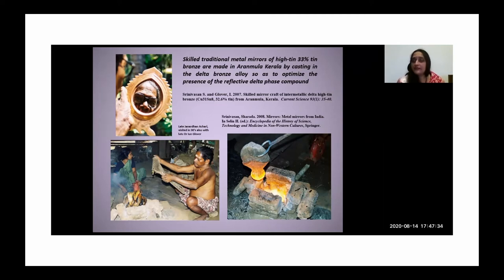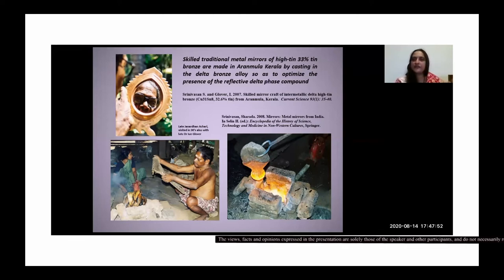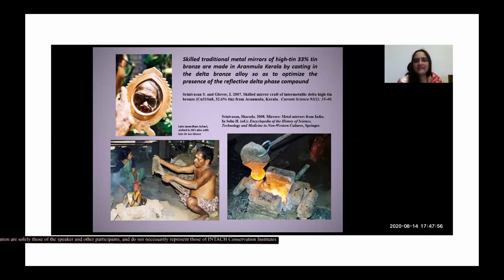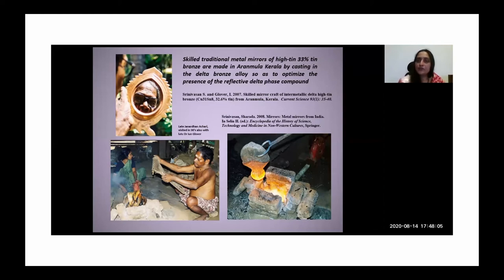And one thing though I must mention is that the Chinese also made a lot of mirrors, and they're famous for making mirrors from very early on. But often the Chinese mirrors, they added lead to make it more castable. But here, the whole process seems to have been that they were very determined to really go for that delta phase and not add lead, because in a way lead is opaque. So it would actually reduce the reflectiveness of the mirror. Whereas this delta phase is actually very much more reflective.